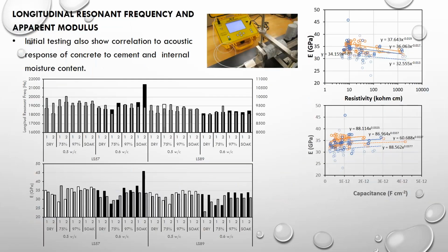We also measured the longitudinal resonant frequencies of the samples at the same time. Again, in these graphs over here, we have the longitudinal resonant frequencies with the rock type, the water cement ratio, and the moisture content. And we have to resolve the modulus of elasticity to get from the resonant frequency. So we have 2 y-axes. One is for the 4-inch samples, one is for 2-inch samples. They correlate well with one another.